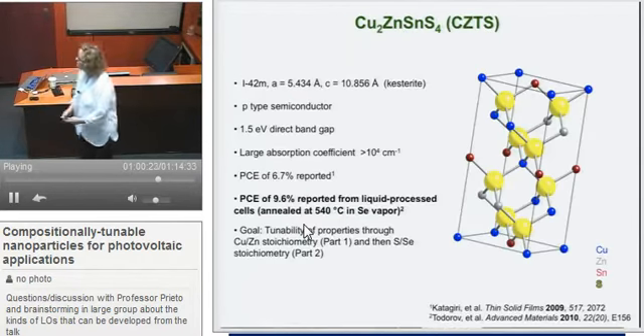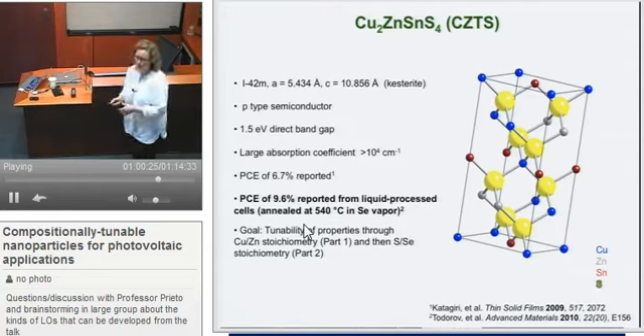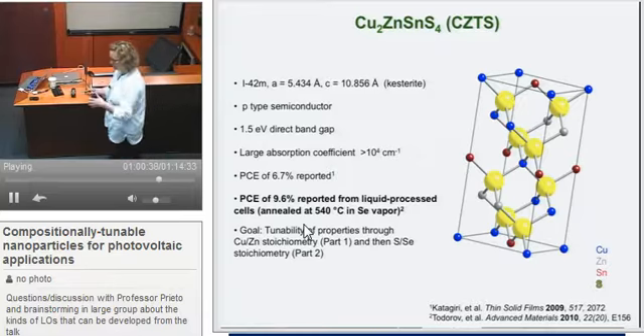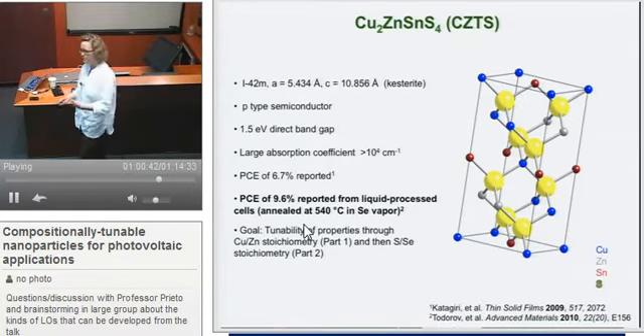Okay, so let me highlight one more thing, and I just have a few more pictures to show you. The paper that I suggested for the workshop involved our efforts now to tune the chalcogen site. And the reason for that is, again, these power conversion efficiencies. The best devices are made out of this hydrazine-based liquid, and then they're heated in selenium vapor at 540 degrees Celsius. And that just seemed really odd to me for many reasons.